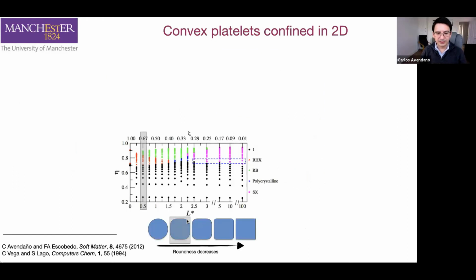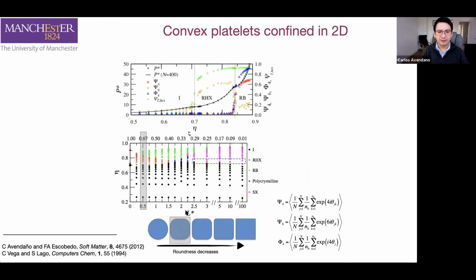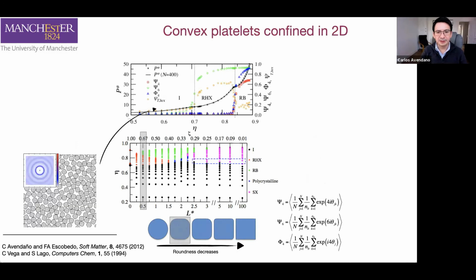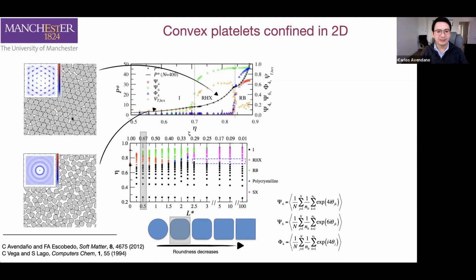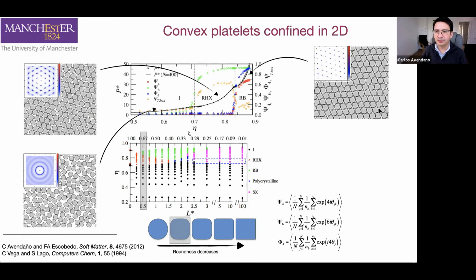And what we observe, first for this particle here, which is quite rounded, is the first low density deformation of the isotropic phase, but then this will transform into this hexagonal phase. So the particles have a square symmetry, but now we can see that that small change in the sharpness of the corner was enough to disrupt the formation of the square phase. And we observe the formation of this hexagonal phase that, if we keep increasing, so here we have pressure against density, if we keep moving in this direction and increase the density, now we will observe the formation of the rhombic phase, which is in complete agreement with the experimental observations.